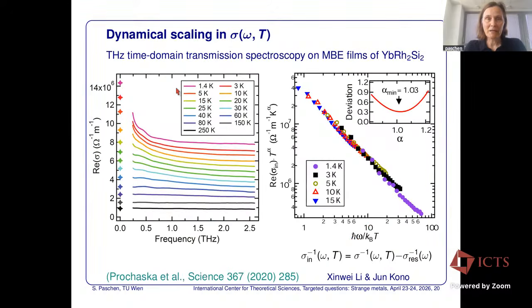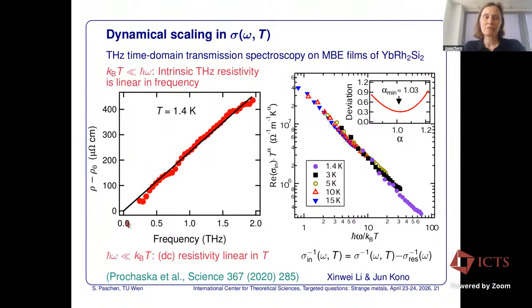So that this is dynamic was investigated by the optical conductivity, or more precisely, the terahertz conductivity, that became possible only after growing MBE films of this material, because this is precise only in the transmission without Kramers-Kronig transformation. And what was found is that the data can all be collapsed with this dynamical scaling analysis here, and the exponent of the temperature is 1. That directly links a linear in frequency response to a linear in temperature response if the other scale is small compared to either the frequency or the temperature.